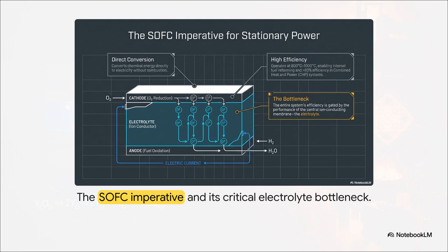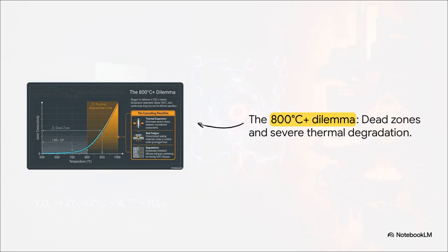As brilliant as the system is, the entire thing is dangerously bottlenecked by a single central component: the electrolyte membrane. If this incredibly thin layer fails, the whole system fails. Which brings us to what we call the 800-degree dilemma, because the environment inside that fuel cell is brutally demanding. If we map out this dilemma, it reveals a massive dead zone below 700 degrees Celsius. In that zone, the ionic conductivity basically just drops to zero. The cell becomes completely useless.